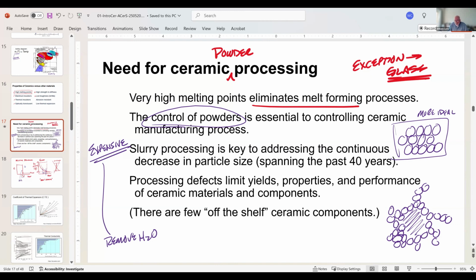The processing defects limit the yields. They degrade the properties and the performance of the material and the components. So what is a processing defect? Okay, so a processing defect could be this. It could be in an otherwise good matrix, a cluster of particles, okay, which does not break up in the process and retains itself as a cluster of particles, okay? This is called an agglomerate.